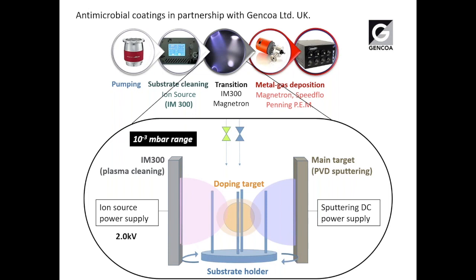What we discovered is it's known around the world that if you deposit a metal oxide material like titania by PVD, bugs don't like it, and there is some antimicrobial activity. What we discovered, or rather Gencoa discovered, is that if we deposit a thin film of a metal oxide and then we use what's called an ion beam to impact the surface and give it a nanostructure, i.e. make it look a lot more like things you see in nature. In nature, nothing's perfectly flat. Well, maybe some things are, but things that are antimicrobial aren't. We discovered that if we nanostructured this surface to a specific morphology, then we increased the antimicrobial activity of this surface by a further 3 orders of magnitude. So we can now generate an ultra hard, inorganic, durable coating, which can provide a log 6 kill rate.